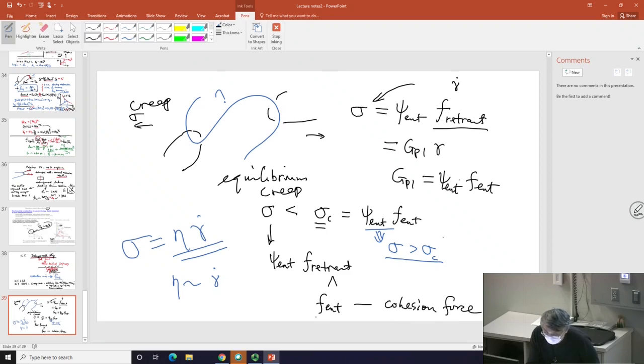The basic point being that alpha is smaller than 1, so that the shear thinning never becomes unphysical. Because when I do that, of course, I have this as gamma dot to the power of 1 minus alpha. And this is always positive. Yeah? And in that limit, I can, by definition, become faster in shear to satisfy the stress you applied.